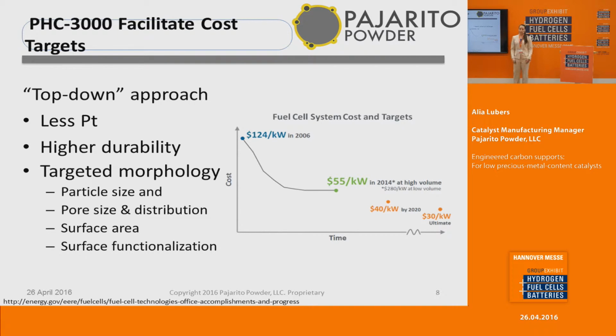And the idea behind developing a good carbon support is to really drive those costs down. So the DOE target projections for the ultimate cost of a fuel cell system is $30 per kilowatt. Half of that is budgeted for the catalyst, which is pretty phenomenal. The reason for that is because platinum is so expensive. If we can drive the amount of platinum that we actually need, we can also drive the ultimate cost targets down as well. How we do this is to produce a carbon support that is highly graphitic, has a particular particle size, and also has particular pores, enabling this optimized three-phase boundary.